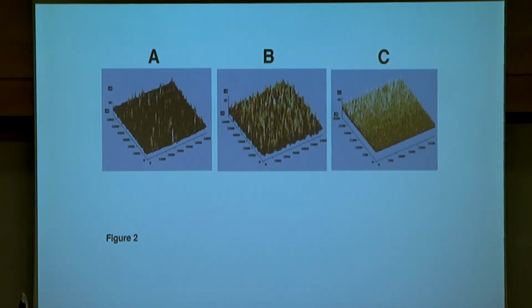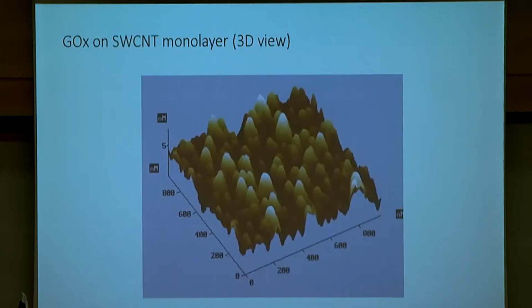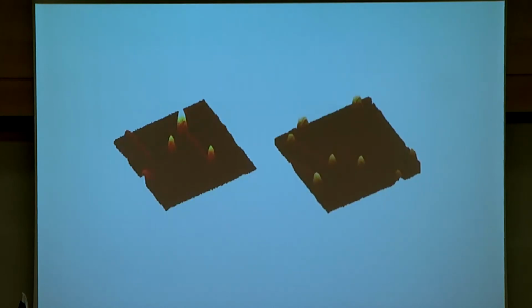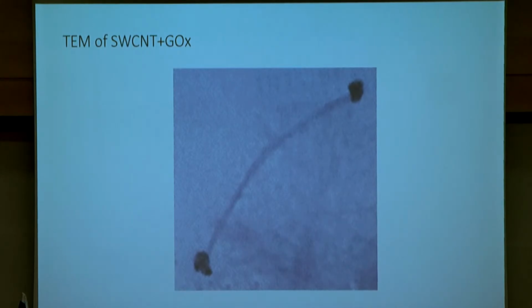and to get the bioelectrocatalyzed oxidation of glucose. Here you can see very nicely the standing carbon nanotubes on this electrode before the reconstitution. You can see after reconstitution the enzymes that were on the surface. And finally, we were able to see at the single carbon nanotube level the glucose oxidase units that are attached to the heads of this carbon nanotube after the reconstitution process.